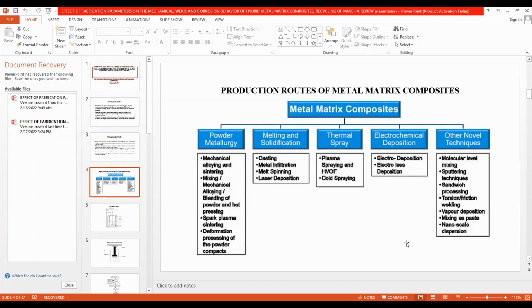Of course, the most common is powder metallurgy, mechanical alloying, sintering, mixing, blending of powder and hot pressing, spark plasma sintering, deformation processing of powder compacts, melting and solidification, thermal spray like plasma spray, cold spraying, even electrochemical deposition, and the latest novel techniques like molecular level mixing, sputtering techniques, sandwich processing, vapor deposition, mixing as paste, and nanoscale dispersion. These are some of the most commonly adopted manufacturing routes.